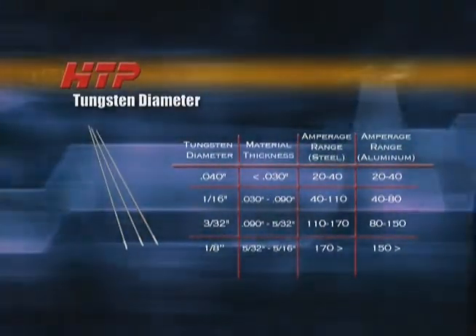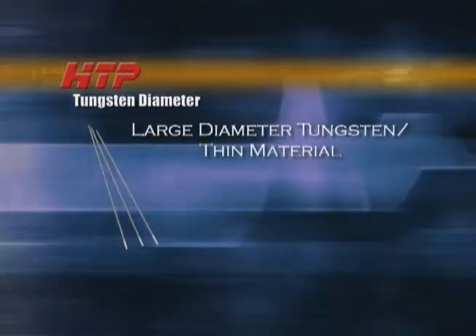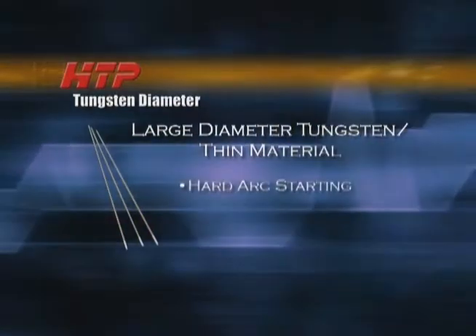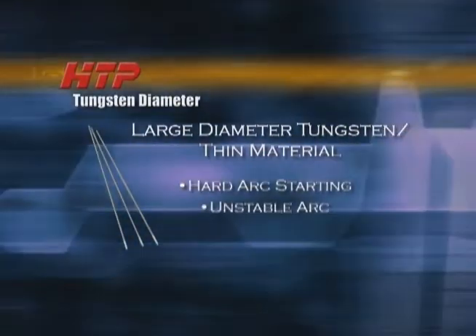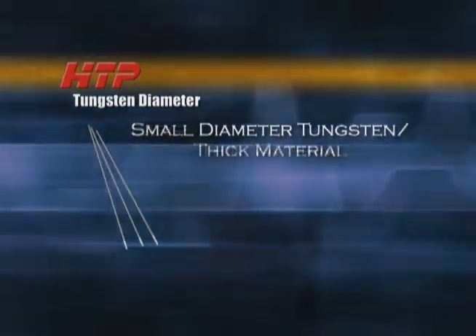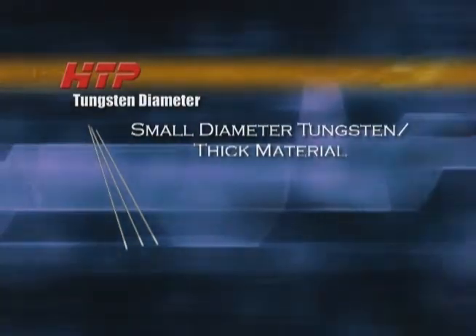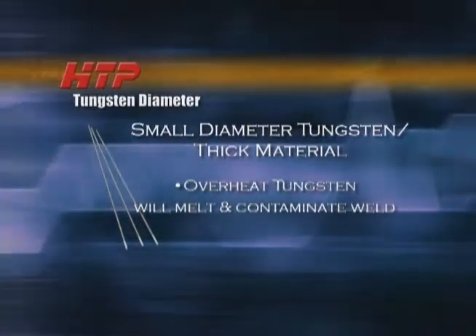The chart on the screen gives you a good idea of the correct size tungsten for different thicknesses and welding amperages. Trying to use a large diameter tungsten when welding thin material will result in hard arc starting and an unstable arc. Using a small diameter tungsten on thicker material will overheat the tungsten, causing it to melt and contaminate the weld.